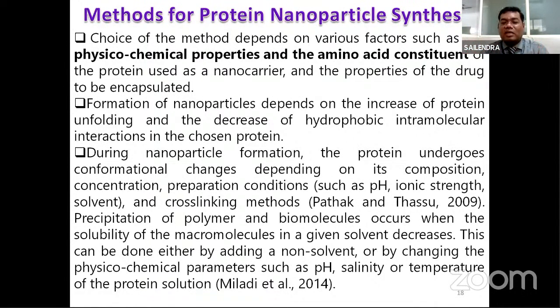So amino acid exchange on the surface and at the center of the protein nanoparticle keeps on going on till it achieves a particular structure where it is going to precipitate, and you are using a cross-linker in order to cross-link those protein structures. Now, different types of methods are there. Desolvating techniques, concentration techniques, precipitation techniques, even high pressure techniques. In all of them you have to get the nanoparticle by solubilizing the protein initially in one of the two solvents, either a water soluble solvent or the organic phase. Apart from that, pH, salinity of the medium where you are performing this reaction, and temperature are all important contributors to how we are going to prepare the nanoparticles.